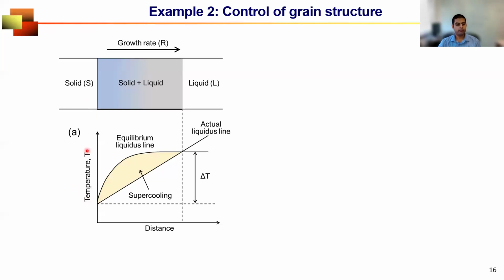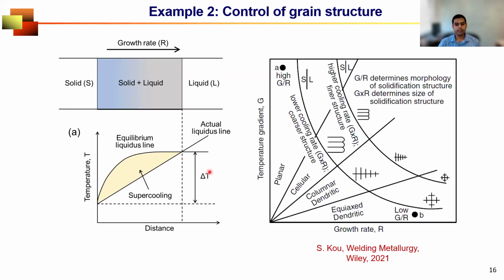If you plot the temperature in that region, you will see there are two things. One is the actual liquidus line, and the other is the equilibrium liquidus line. The difference between these two is called supercooling. For any solidification process to happen, there has to be supercooling that drives it. This temperature difference divided by distance, which is called the temperature gradient, represents whether we will form columnar grains or equiaxed grains.